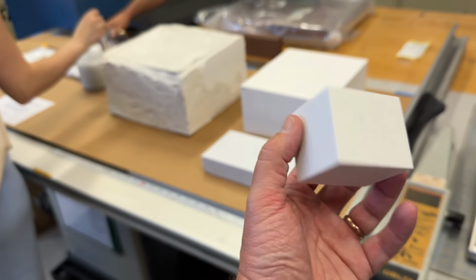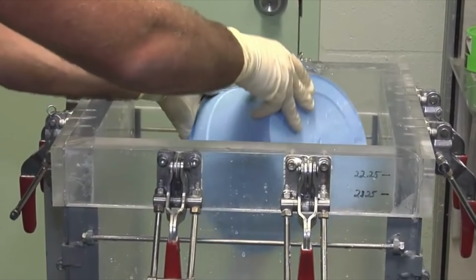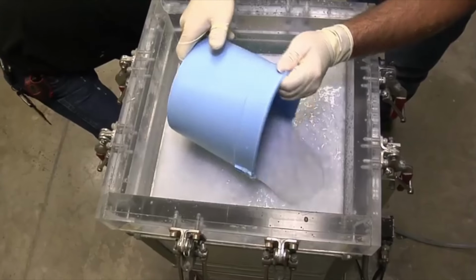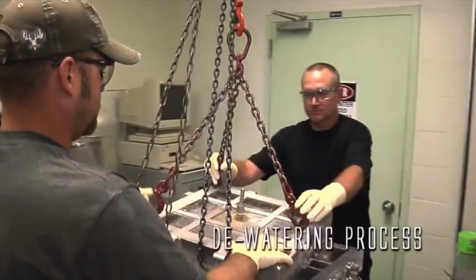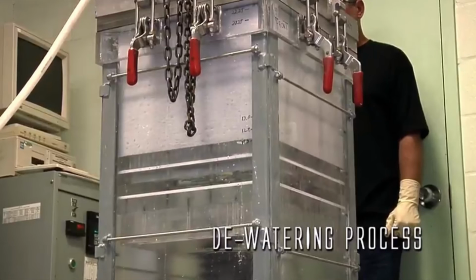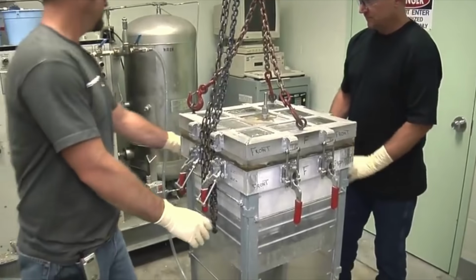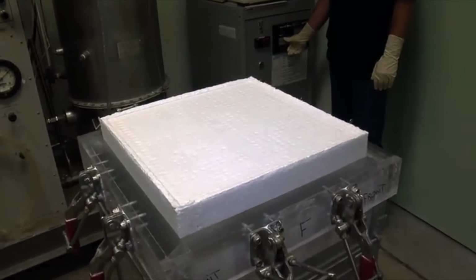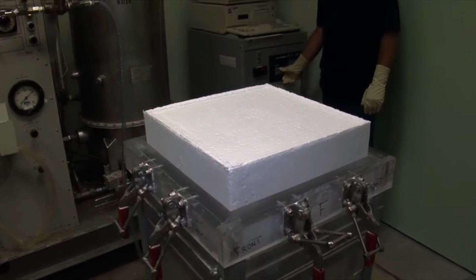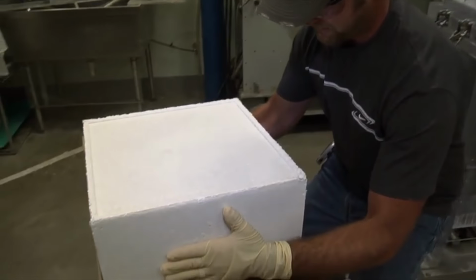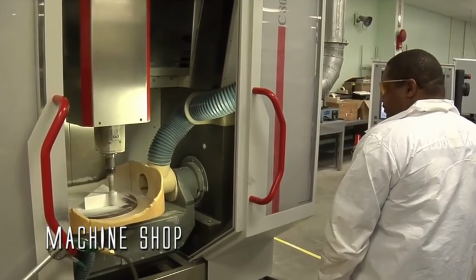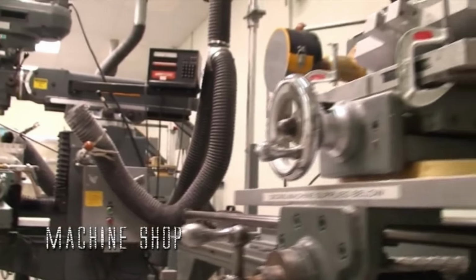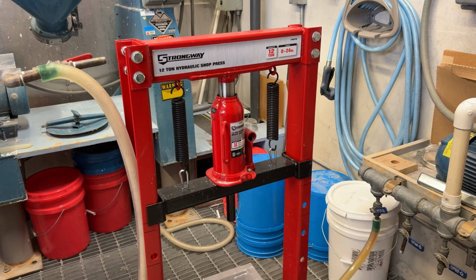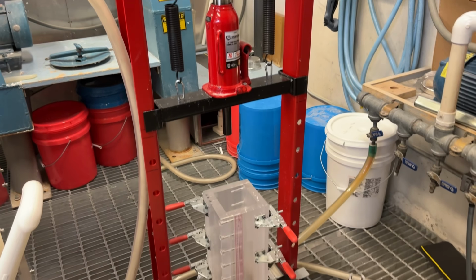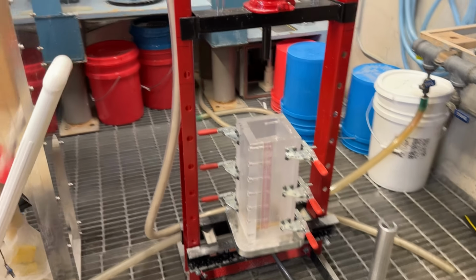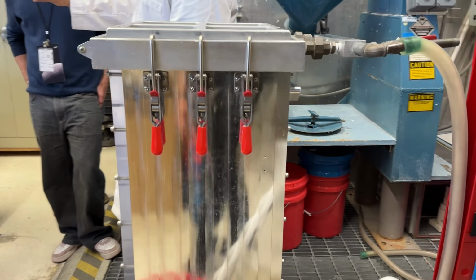And the higher the density, the less effective it is as a TPS. You have a weaker strength through the thickness, stronger through the sides, and its ability to transfer temperature from outer to inner mold line is very limited because the fiber direction is horizontal, and it's about 94% air. So air is not a good conductor. The heat hits those fibers and it radiates out horizontally with the outer surface, and it will maintain the majority of its heat just at the outer surface. So with one of these tiles, with what we call an emittance coating, you could have a 2,400 degree outer temperature, and 2 inches away, it's maybe 100 degrees.